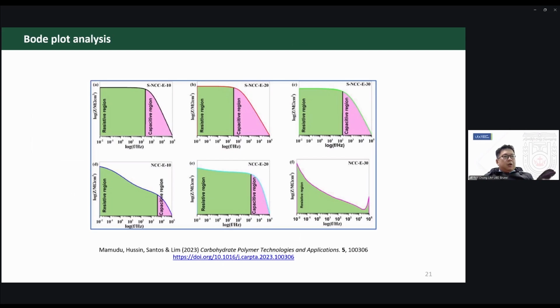So here our Bode plots are: the ones on top are from the sulfated nanocellulose, the ones on the bottom are not sulfated, just the nanocellulose on its own. This is the Bode plots after 30 days. And you have normally a capacitive region indicated in pink, and then there's the resistive region.